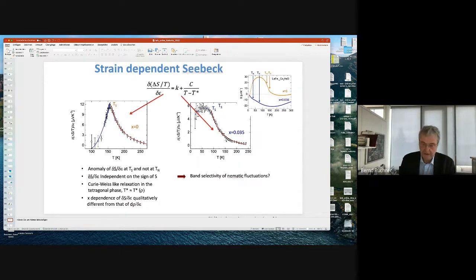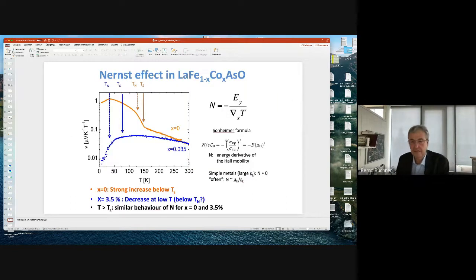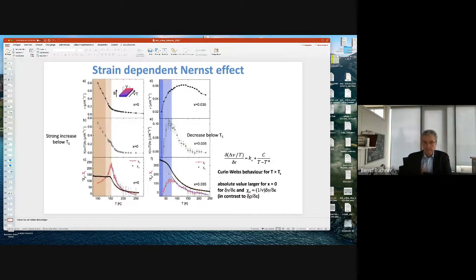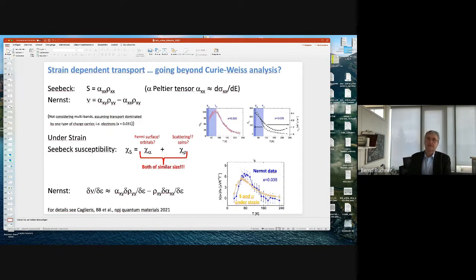So I think I'll skip the details a little bit. We can do the same for the Nernst effect. Nernst effect typically is zero in simple metals, but here in these systems we have a finite Nernst effect which changes a lot upon doping, and we can even follow these dependencies as a function of strain, these susceptibilities if you want. Again, you can get this Curie constant. That's easy. But you can also do a little bit more than the Curie constant.